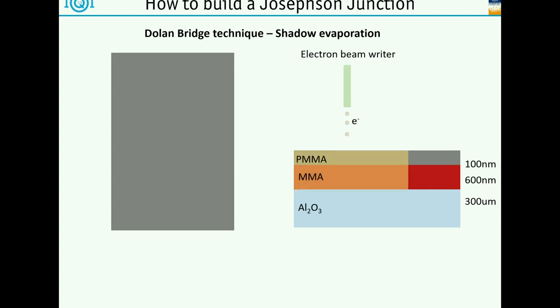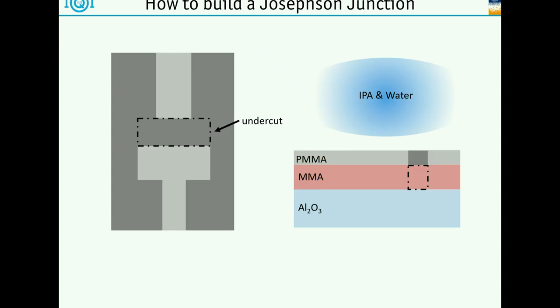What we then do is we take an electron beam and we put electrons on places wherever we want to change the chemical structure of this resist. And depending on the dose, we can only change, for example, the lower one, or we can change both of them, because this one will change its chemical structure at a much higher dose than the other one. So we can then take, for example, isopropanol and water to wash away everything we have developed, everything we have hit with this electron beam, and what we then get is a mask which looks something like this from the top. Here, this part would be that bridge you can see here, and that part, which I should have maybe drawn in blue, really goes down onto the sapphire.